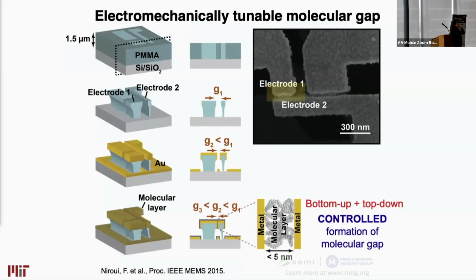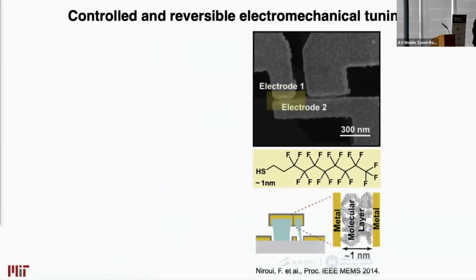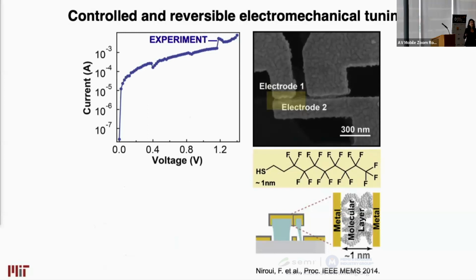We deposit our molecules, and through this process, intentionally induce collapse of our relays such that the molecule is sandwiched between the gap. So an original gap fabricated at much larger dimensions can now be reduced to sub 5 nanometer in size. Now, if you fabricate such a device using this fluorothiol molecule, you can get a current voltage characteristic exponential in form, expected of quantum tunneling.